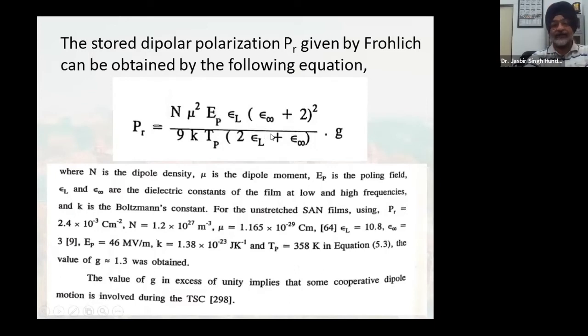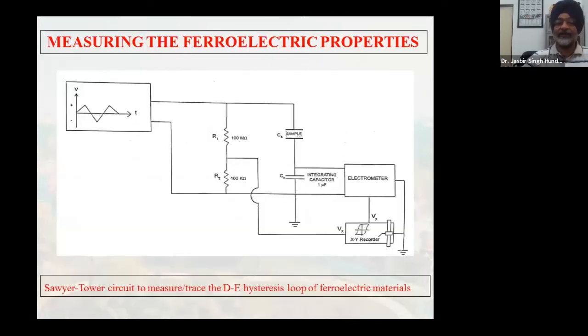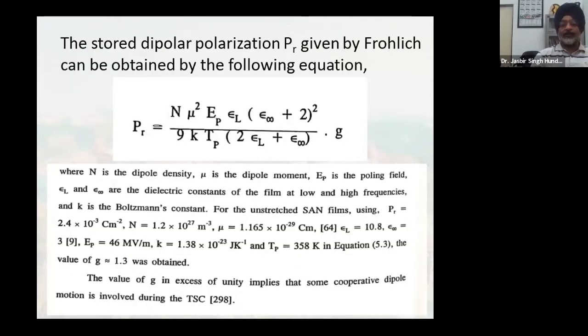But the essential thing is that we already have these values. These are all given here. And we found out the value of G. If the material gives a cooperative behavior of the dipoles, then G should be greater than 1. Then only you are going to get what you call hysteresis loop. Otherwise, the hysteresis loop won't come. So there has to be a cooperative binding between adjacent dipoles. Then only you are going to get hysteresis. Then only the material is said to have some kind of spontaneous polarization, which is already there.